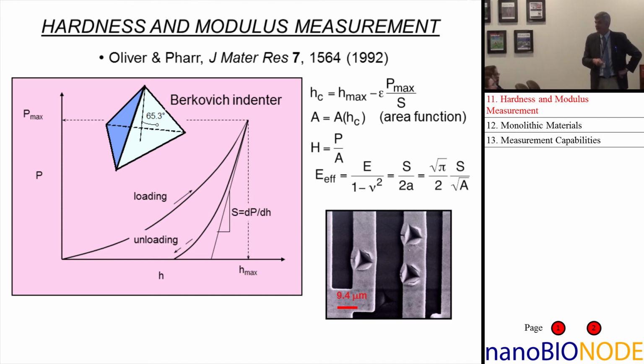And so we always like to point out there, too, that we're not measuring Young's modulus directly. We're measuring the effective modulus. So if you want to get Young's modulus out, you've got to know what Poisson's ratio is independently. Fortunately, Poisson's ratio, at least in most metals and ceramics, is about 0.3. And so when you square it, it ends up being 0.1. And so it's not terribly, terribly important here, depending on what your level of accuracy is that you need. But I do need to point out, we don't measure modulus directly, we measure effective modulus.